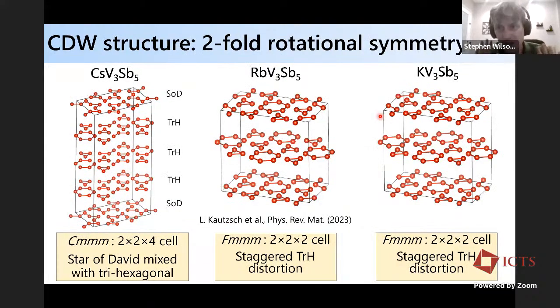Okay, so now focusing on the real space part of the charge density wave state. These are the patterns of charge density wave, the structure in the charge density wave phase as determined via X-ray diffraction measurements. Focusing here on rubidium and potassium, in the middle and the right of the screen, what you can see is that in a single Kagome plane, the Kagome lattice breathes in this 3Q distortion, a so-called trihexagonal distortion, where the Kagome net breathes into a pattern of triangles and hexagons. Then as you go from one layer to the next, they're phase shifted by half a unit cell, the so-called pi phase shift. That breaks the rotational symmetry of the unit cell, and you end up with a 2 by 2 by 2 three-dimensional charge density wave superstructure, okay? This pattern is the same for rubidium and potassium.